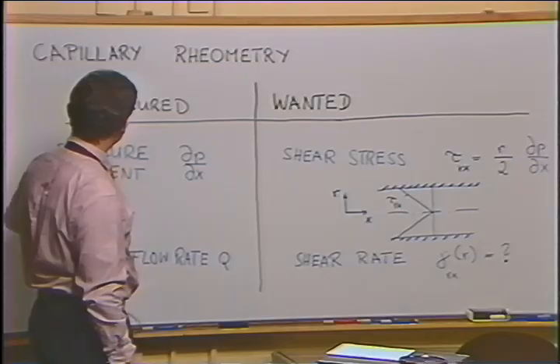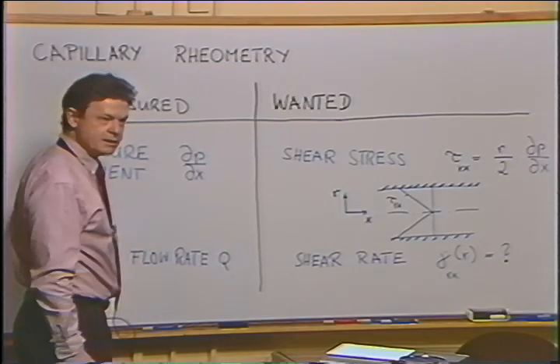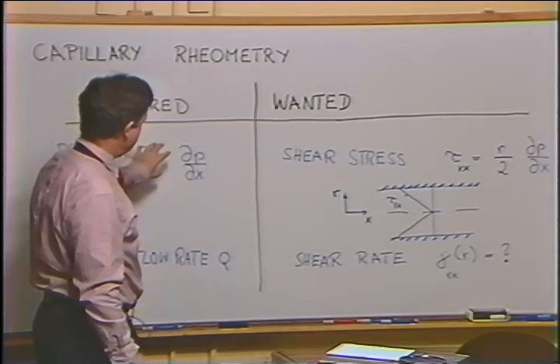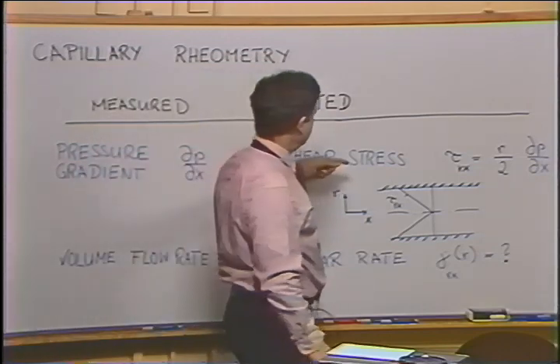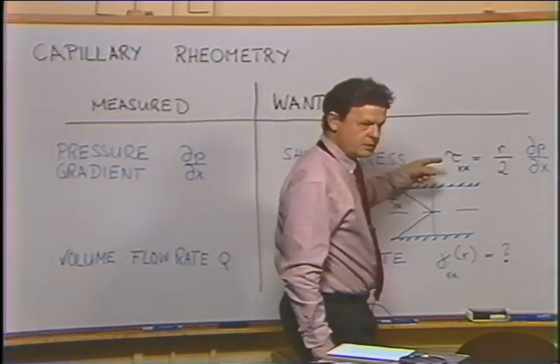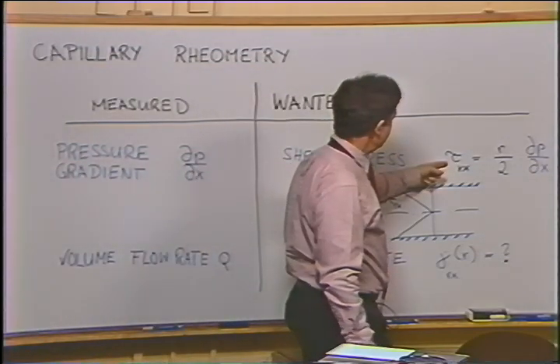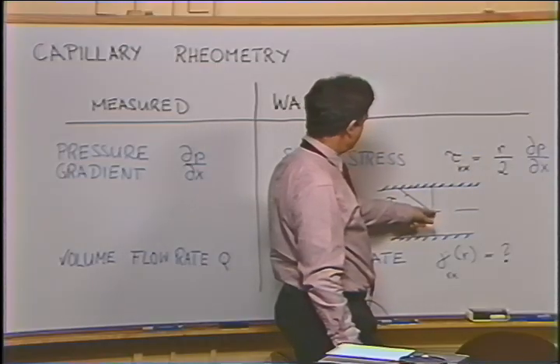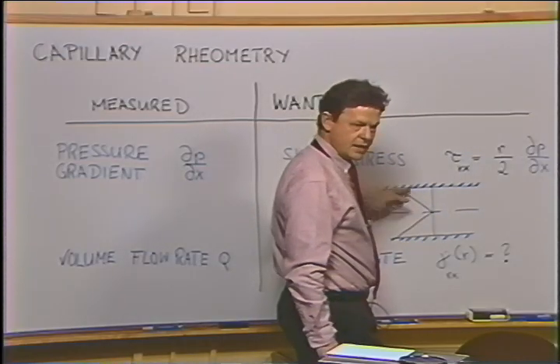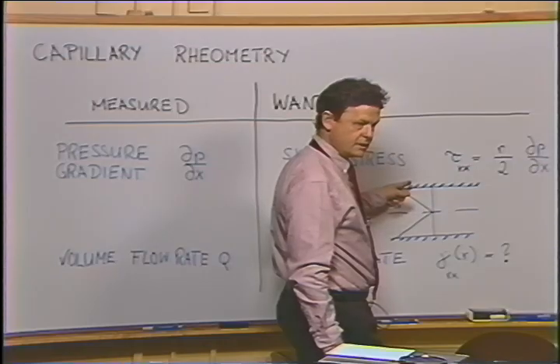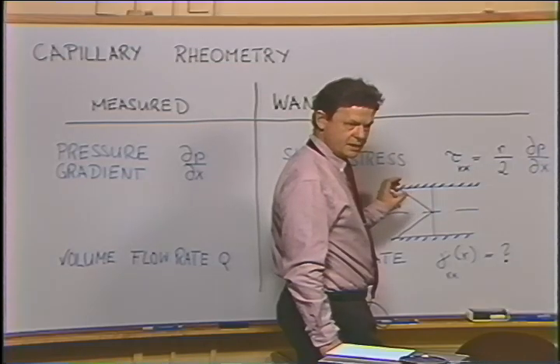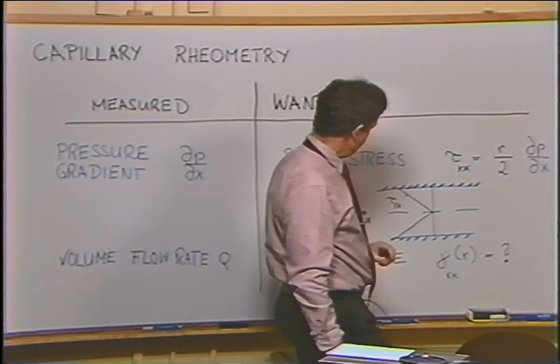Now the analysis of the experiment is very easy with respect to the stress, with respect to the shear stress tensor. We would measure the pressure gradient in the capillary, and this information would be transferred immediately using a momentum balance into the shear stress as a function of the radius, and you can see that there's a linear relation between the radius and the shear stress. We will use that in a moment, so keep that radial relation in mind.